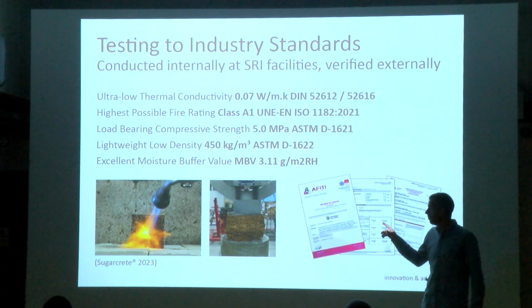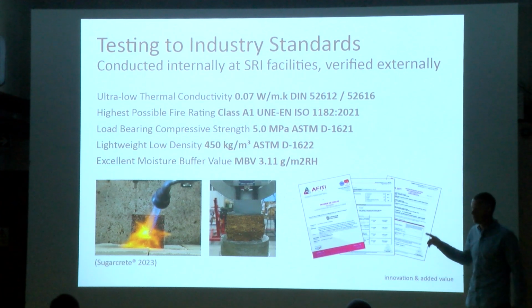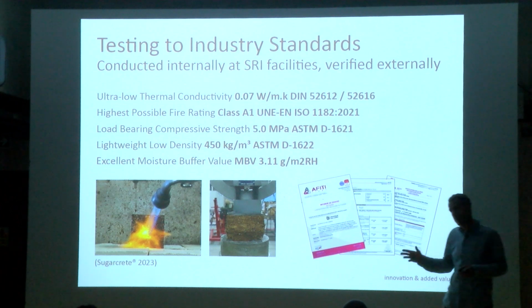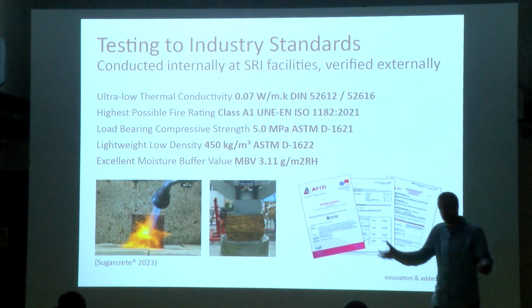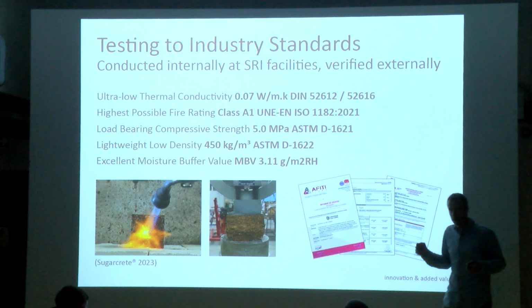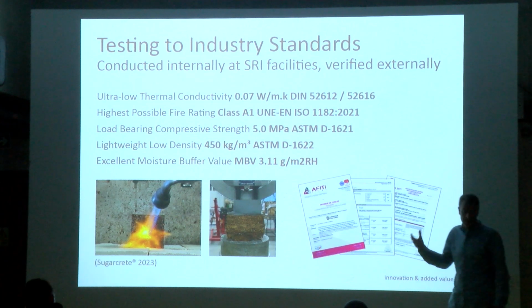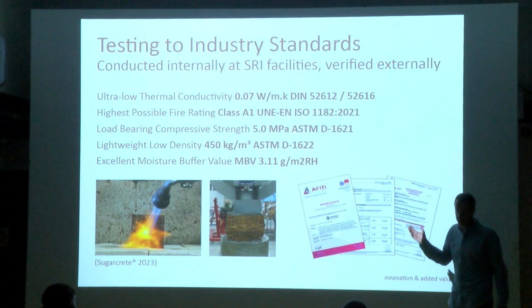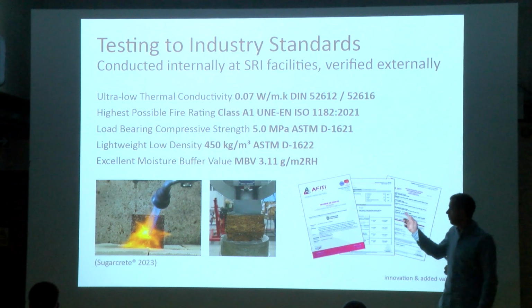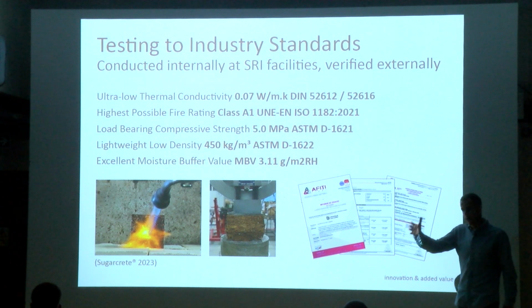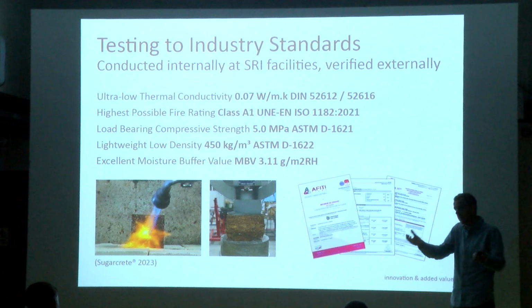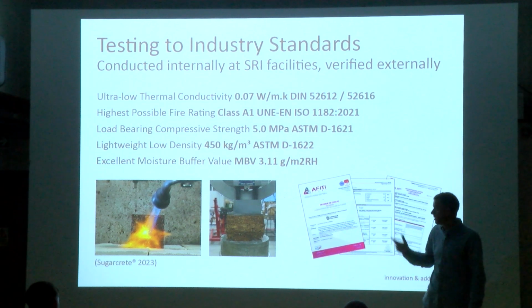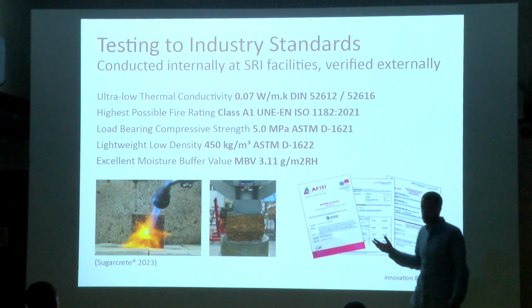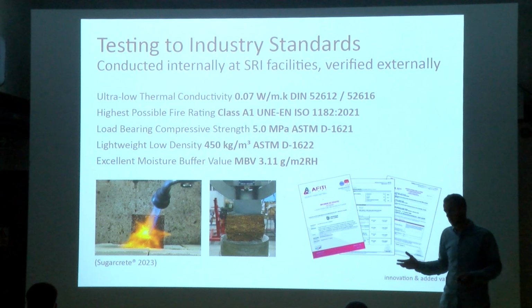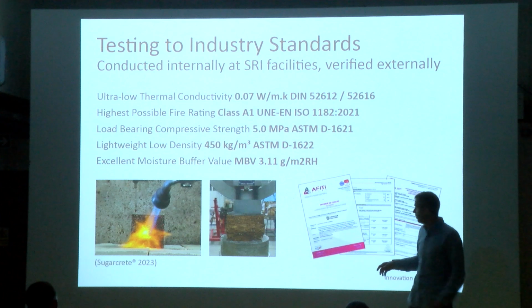And it has very good moisture buffer value, which I don't know if you're familiar with it, but it's a property that biomaterials do very well, which means that they are able to absorb humidity from the environment. So in areas like India, where there is a lot of humidity, depending on the season, but the humidity levels can reach very high numbers, having a wall made of a material that can take part of the humidity and then release the humidity once the environment dries is key to somehow control the passive cooling and the passive heating of the space.